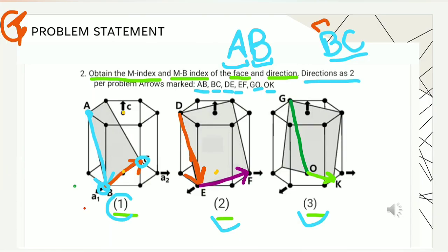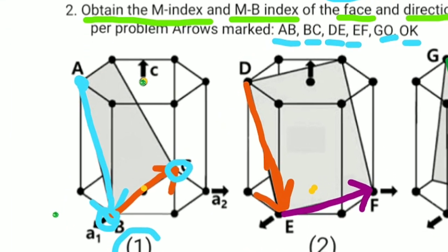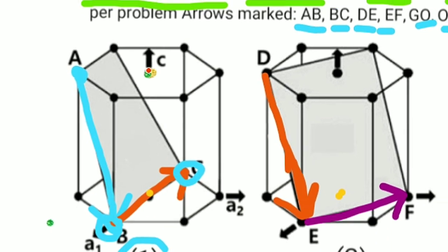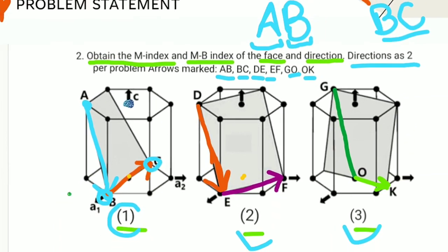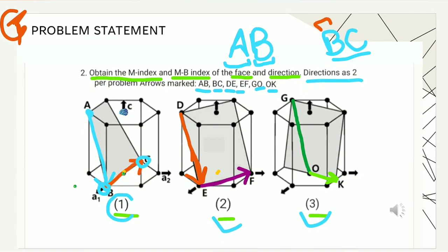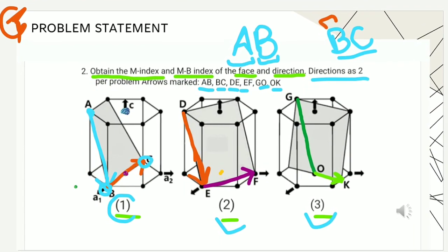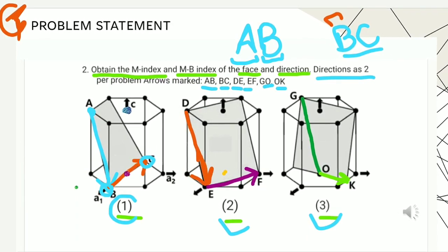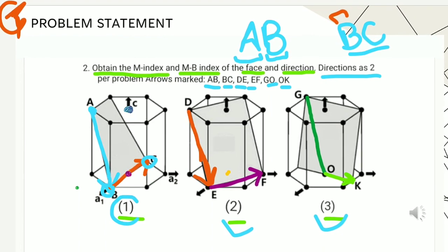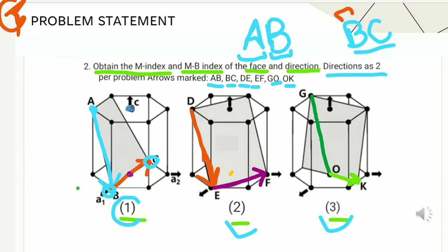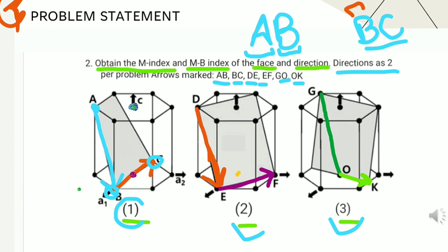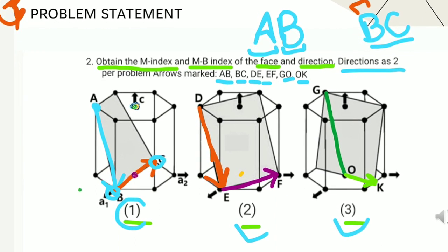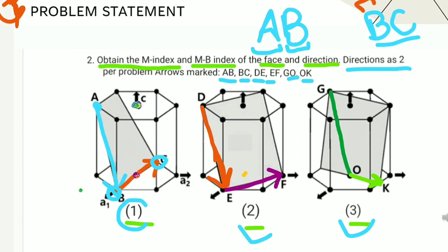And I would love to mention one thing here, that for planes, as we saw, we chose this point as origin, the one I'm showing you, because of the problem with the origin down at the basal plane, as it was passing through the plane. It was a point on the plane also, and that was not allowed in the rules we have established in order to find our Miller indices for the planes. Hence we chose this point above, on the roof plane, as origin, but for directions I chose the origin on the basal plane.